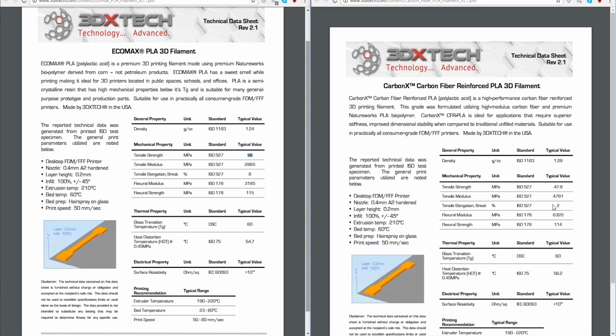And we see that there with a 2% elongation before break, and then a very interesting 8% for PLA. Because normally when you go on the NatureWorks docs, it says that it has elongation of like 3 to 4%. But we'll go off of these guys. So 4 times more elongation before breaking. So this is a way tougher material than the carbon fiber reinforced.